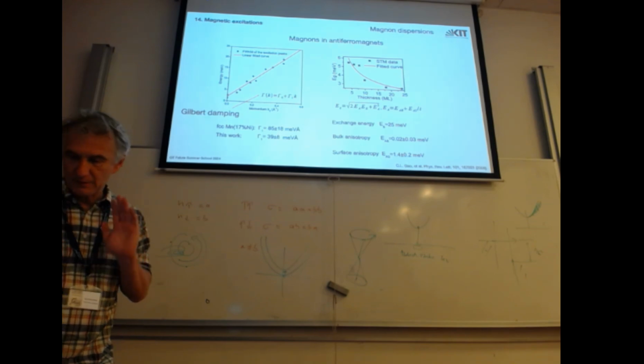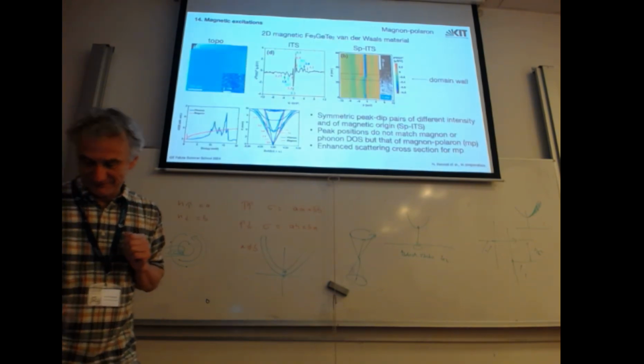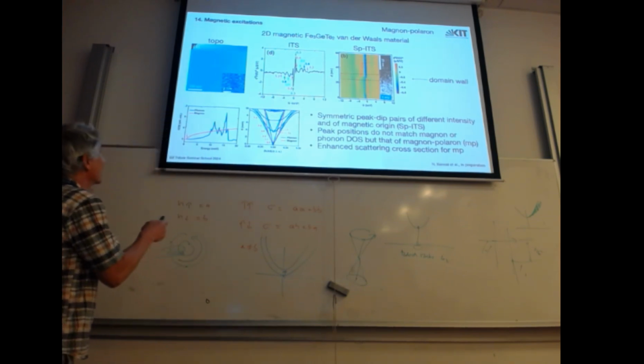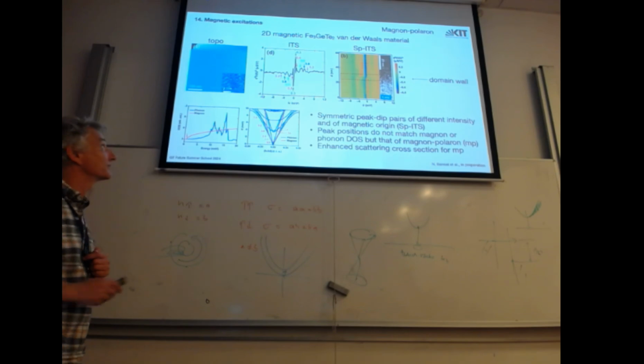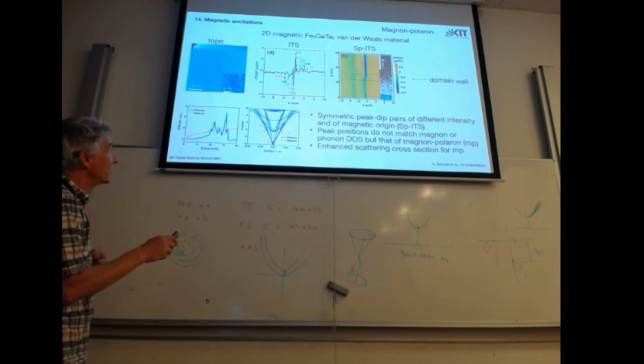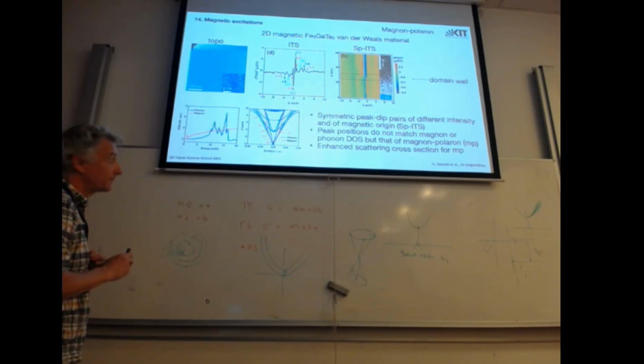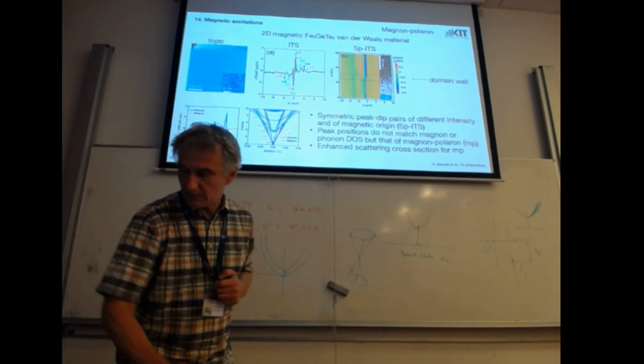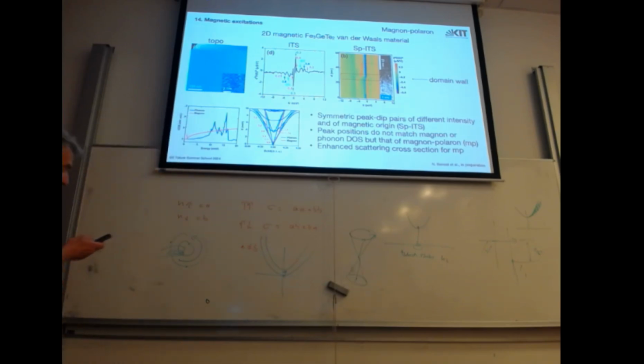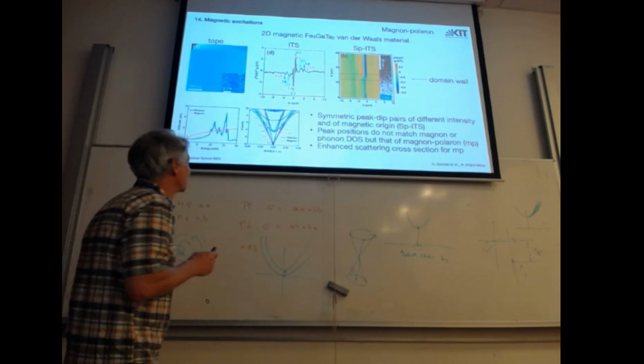Okay. I'll show you something unpublished. Let's go to two-dimensional ferromagnets. This is iron germanium telluride. It's a magnetic van der Waals material. Let me first show you the data. So the background is pretty flat. Inelastic tunneling spectroscopy tells us there are a lot of peaks: 0.3, 0.8, 2.3, 3.8, 5.2 meV.